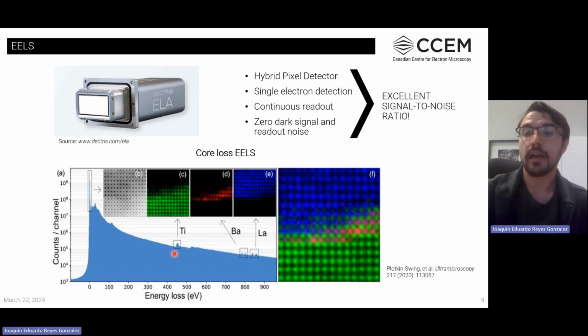They also allow for great signal-to-noise ratio in spectrum mapping or spectrum imaging. So for instance, here we have from left to right, the image coming from the zero loss peak, which results in an image similar to that of a bright field STEM.